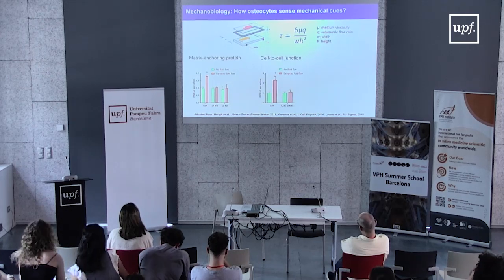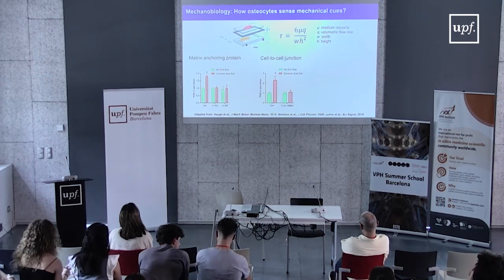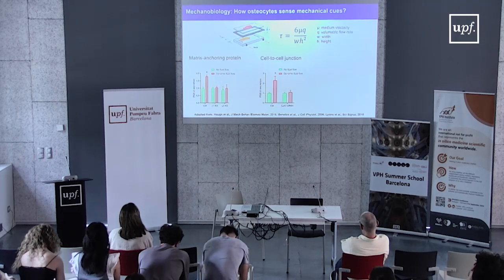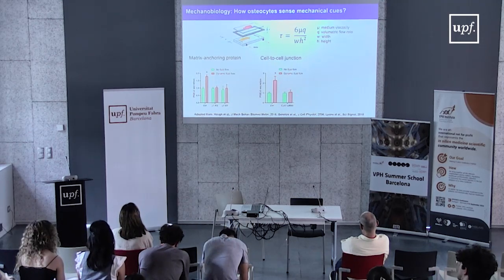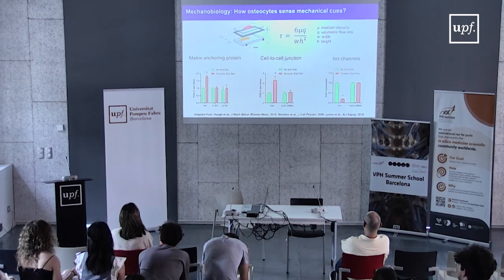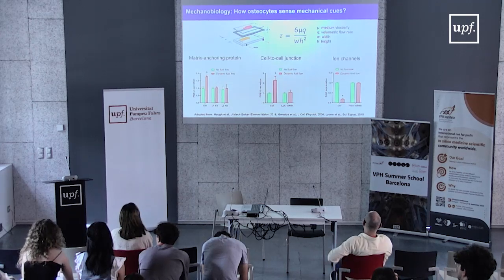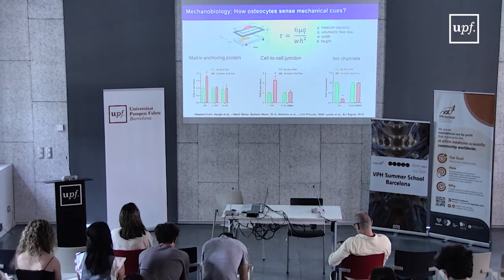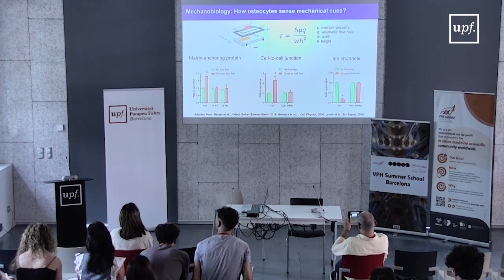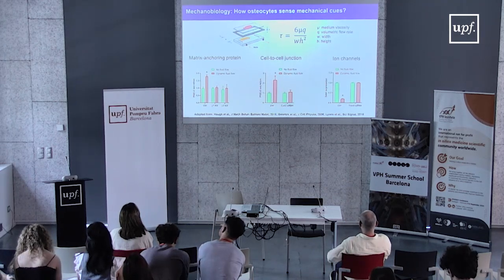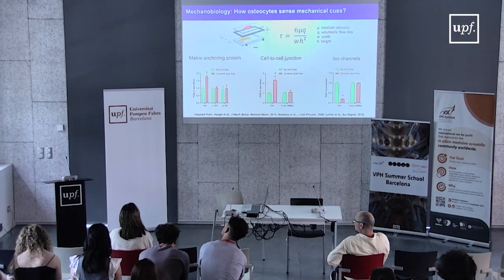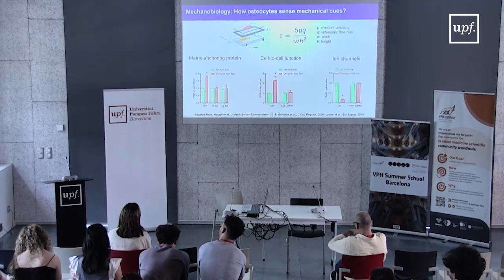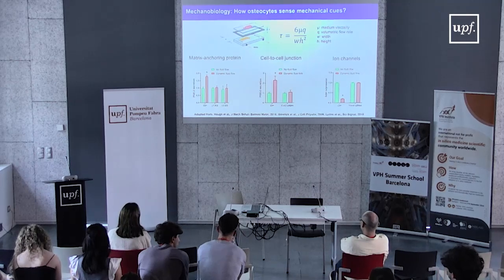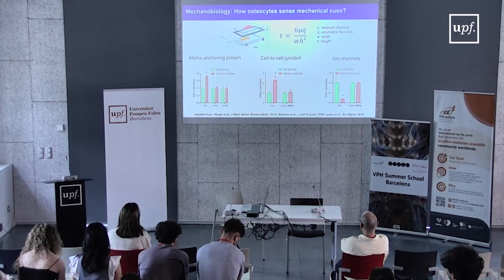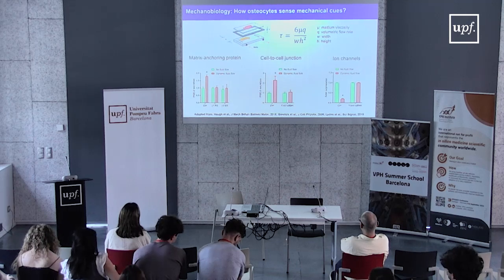If we do the same by knocking down with siRNA the cell-to-cell junction, by inhibiting connexin 43, here again, osteocytes are no longer capable of responding to dynamic flow. And finally, if we knock down TRPV4, which is an ion channel sensitive to mechanical stress, osteocytes still cannot respond to dynamic flow. So it's really these three things, ion channel, cell-to-cell junction, and matrix anchoring protein, that will sense mechanical forces and will induce, through the cytoskeleton of the osteocyte, a response up to the nucleus.